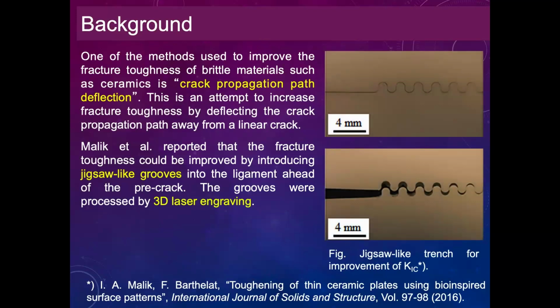This figure shows the CT specimen with jigsaw-like grooves, which were processed ahead of the artificial crack as shown here. When we apply an external load to this CT specimen, the crack opens around here, and then the tip of the crack is guided along the jigsaw-like groove as shown here, which leads to an increase of the fracture area.